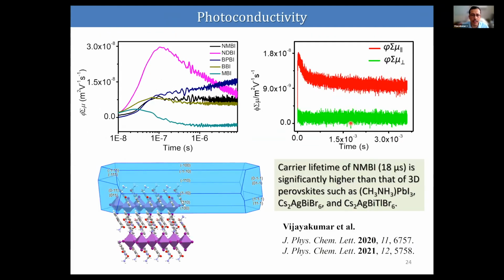And because of that, these materials containing the naphthalene imides show very good conductivity. Again, we did the time-resolved microwave conductivity analysis. And the one-dimensional structures we developed show a very good anisotropy along the crystal axis. And not only that, the charge carrier lifetime of one of our materials is very high, 18 microseconds, which is significantly higher than the well-known methyl ammonium lead iodide, as well as several lead-free double perovskites.